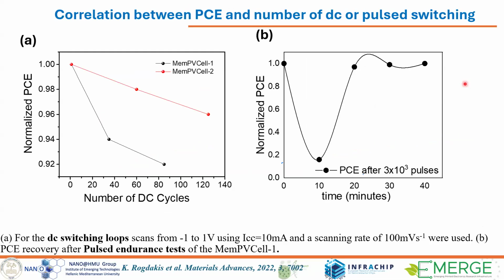Here, the important point is what about PCE? When we apply all this bias, all these pulses in the device, what about the power conversion efficiency of the device? We have shown that depending on the stress, so if we make DC JV characteristics, PCE is not affected so much. We have a strong suppression of PCE if we send pulses, for example, for endurance evaluation, but we monitor the PCE on time and we see a recovery after a few minutes. So we don't have any permanent damage of the device, just ion migration upon sending some pulses, but the system is restored after a few minutes.